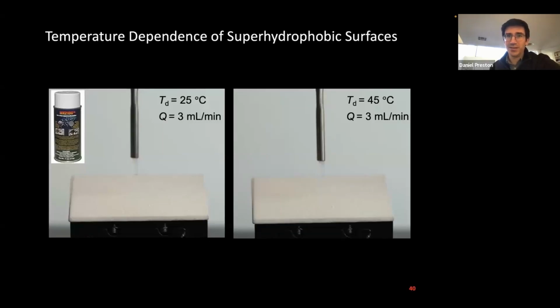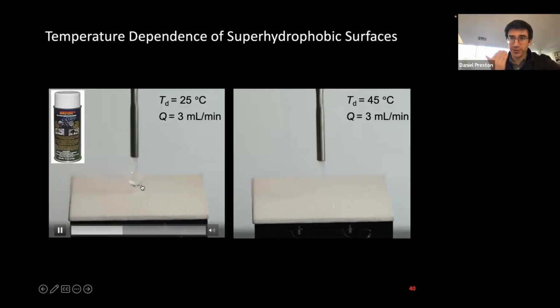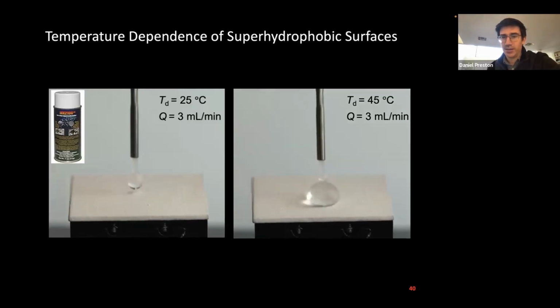But it turns out that there's a temperature dependence of the superhydrophobicity in terms of the impinging fluid. So in this case, we have a water droplet. On the left video, the water droplet sheds the surface easily at a very low inclination angle, maybe just a few degrees of inclination, and the drops roll towards us. But if we take the droplet temperature, these are water droplets, and increase it by just 20 degrees Celsius, and watch the video on the right, we get a lot of pinning effect. We get this big droplet growing on the surface that's much harder to roll off. And so this is maybe not the desired behavior. We're requiring maybe much higher shedding angles as the temperature of the impinging water increases. And if we watch this over time, it will potentially even get worse.